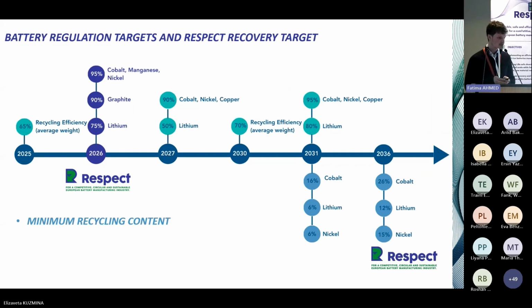I will quickly come back to the recovery targets that are set in the project. Our project will end in 2026, and we target to recover around 95% of cobalt, manganese, nickel, 90% of graphite, and 75% of lithium.